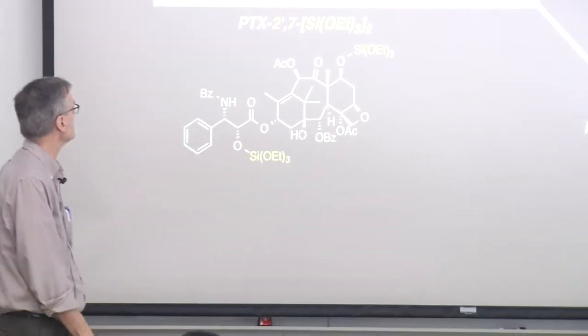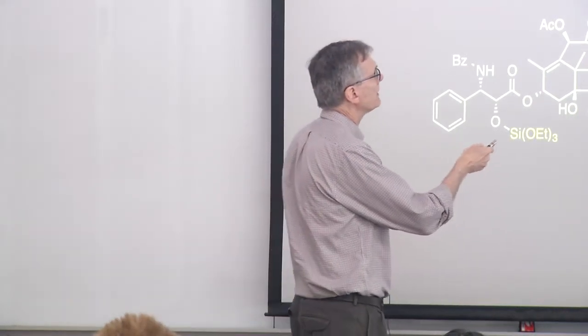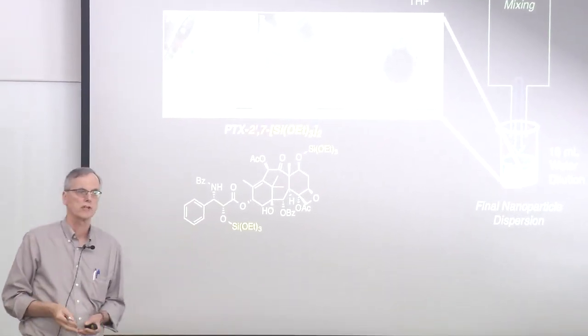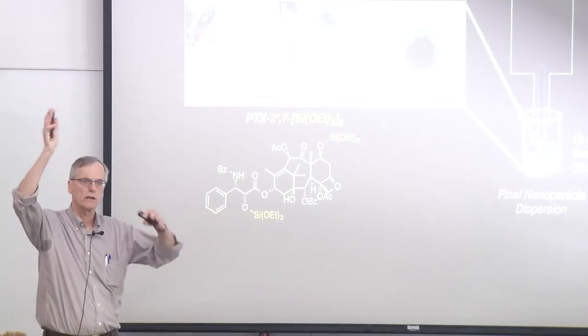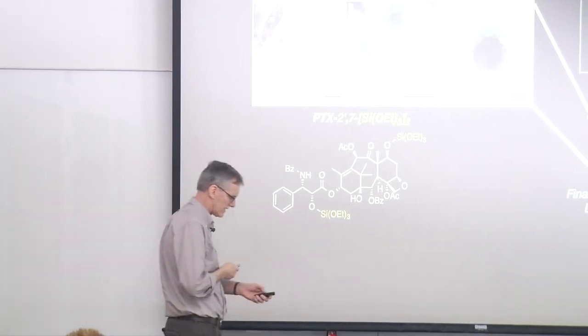For flash nanoprecipitation with the bis-ethoxy derivative — and we've done these experiments with a dozen and a half other derivatives — we get a final dispersion that's stable indefinitely. For four days we don't see much change in DLS measurements of aggregation size, and we don't see obvious loss from the core when put into pure water. We can easily achieve up to 50% loading of the silicate small molecule inside the core of these materials. We can characterize these particles by cryo-TEM — low-temperature vitrified glass — seeing particle size and distribution at 200 nanometers scale.